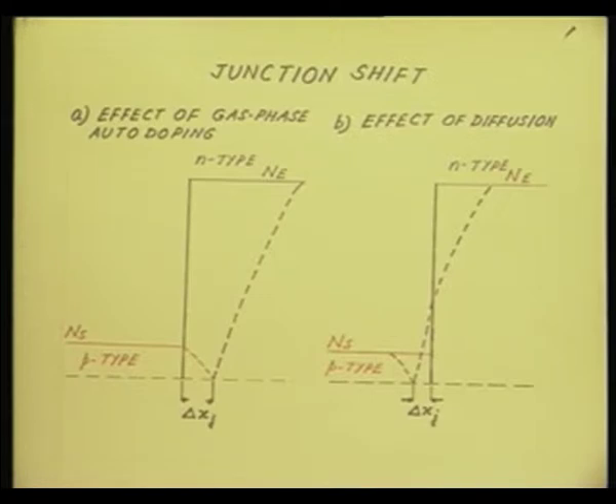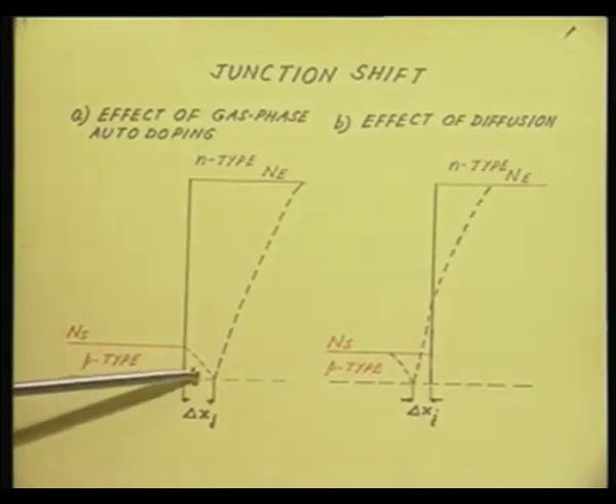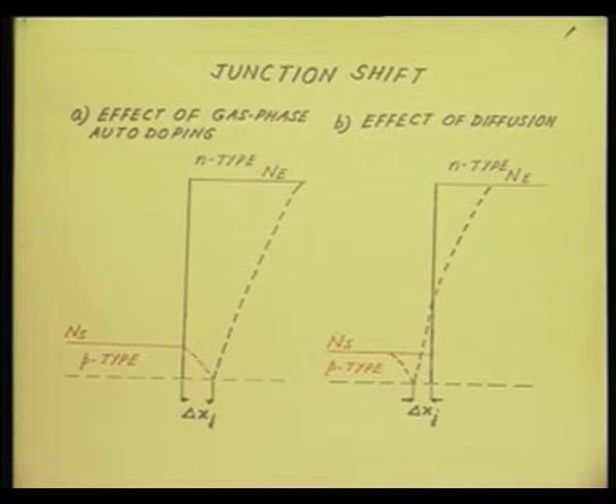This is the red dotted line showing that the p-type dopant is reintroduced in the epitaxial region. And that is why, even though I wanted to grow an n-type epitaxial region, near the junction I find that the junction has actually got shifted into the epitaxial region. The p-type region has actually extended inside the epitaxial region in figure A. Do you notice that the p-type region, this red region, has actually extended into the epitaxial region, and therefore, the junction is now here. The delta xj denotes the amount of the shift, and the junction has got shifted inside the epitaxial region. So, this is the effect of gas phase auto-doping.